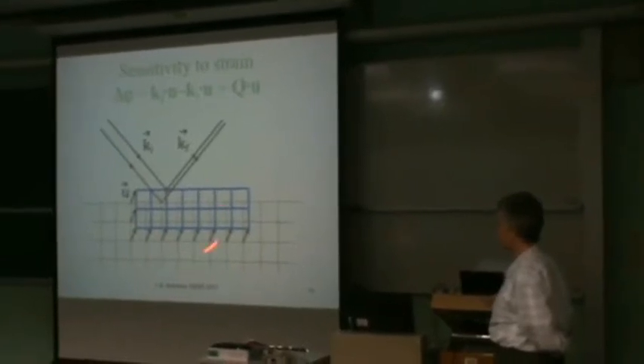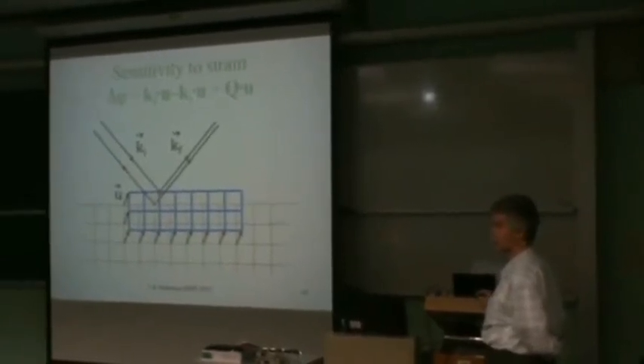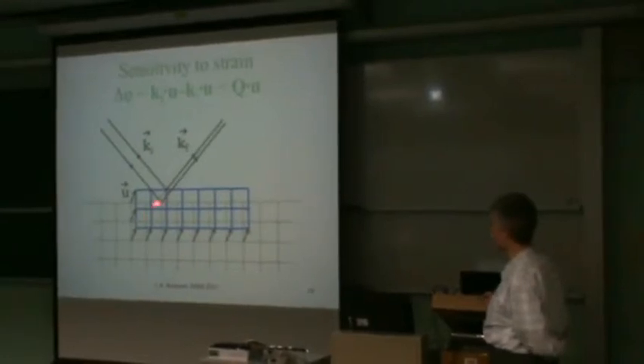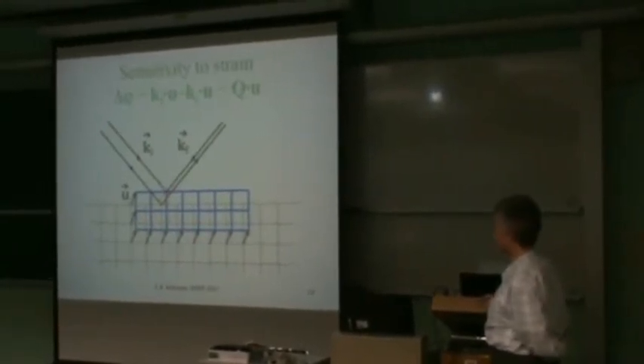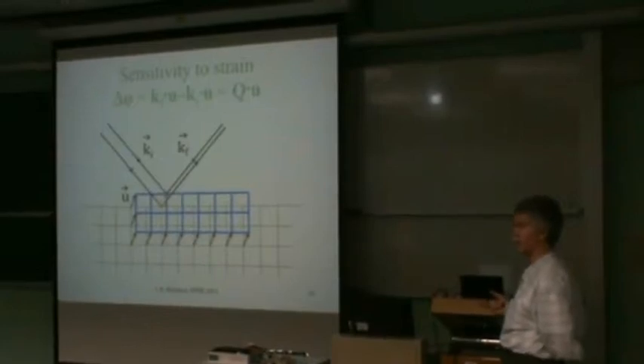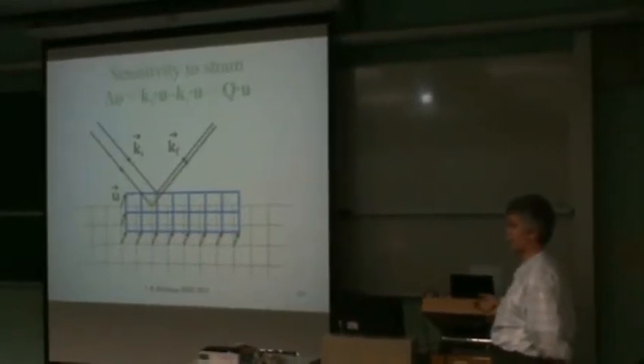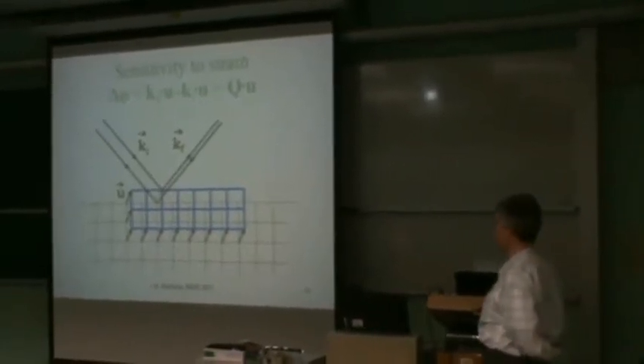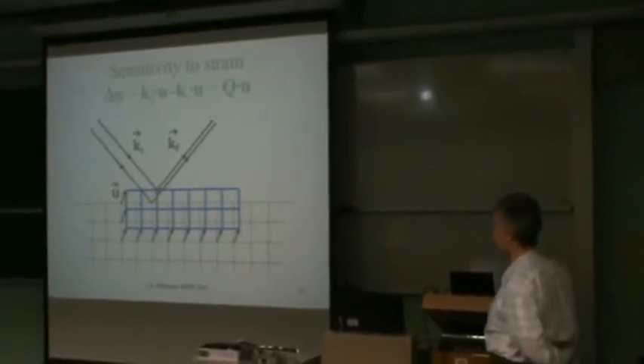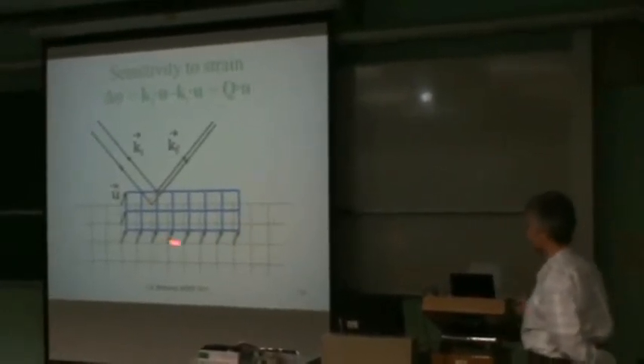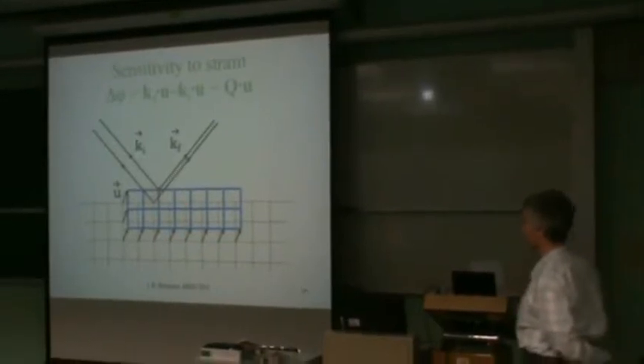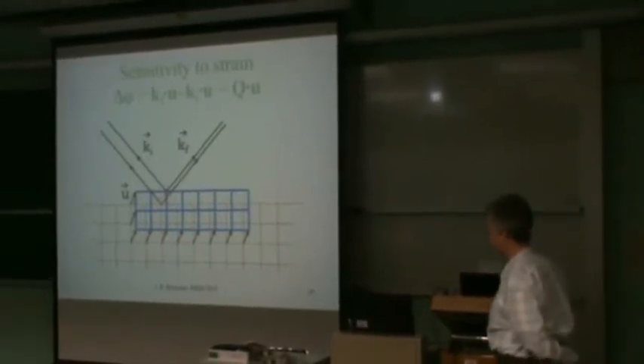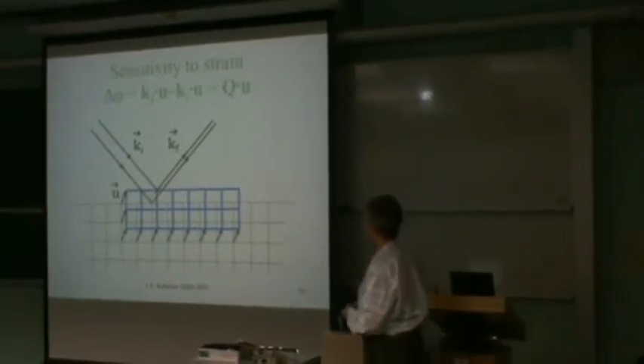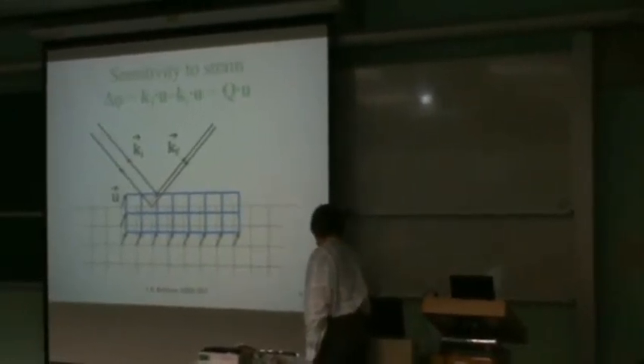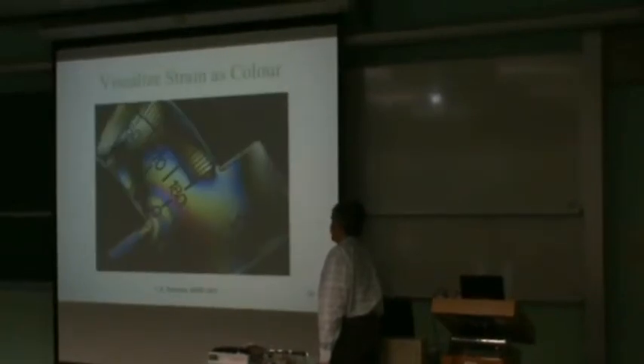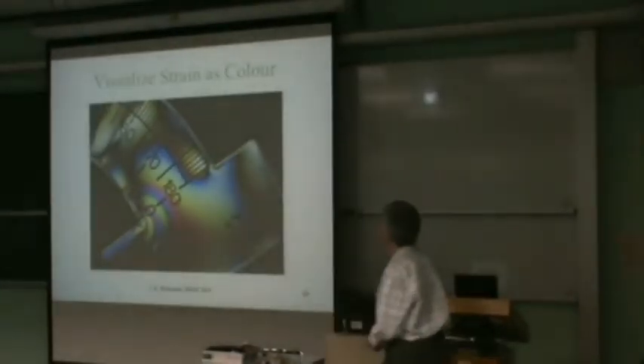But it also tells you exactly where the problem that I was referring to earlier comes about. Because if you have a distortion of more than 2 pi, it's indistinguishable from a distortion of 0. And so there is a wrapping kind of behavior that takes place. If the distortions are too large, it is possible, but it becomes rather difficult computationally to extract those. So it's very good for looking at small strains, but not so good for looking at large ones.